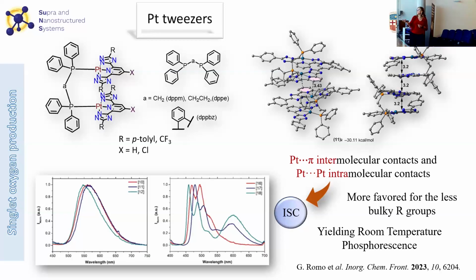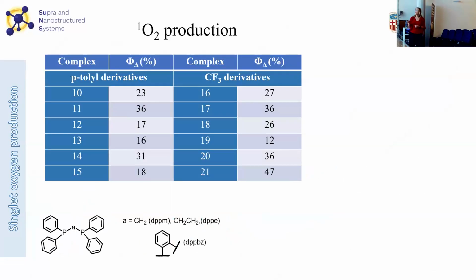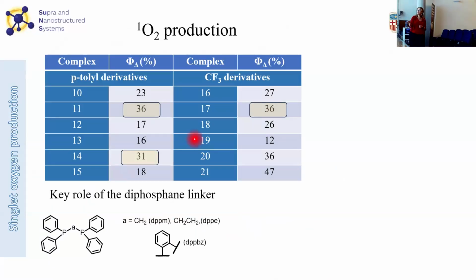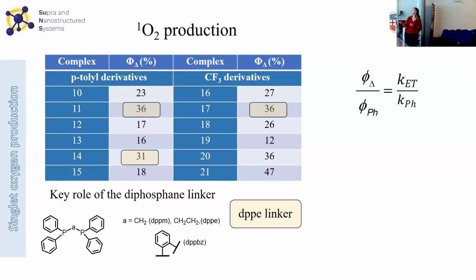And this is due to the presence of this platinum center that is enhancing again the intersystem crossing. So we were previously convinced that in fact this part of the molecule, the platinum and ligand, should be responsible for the singlet oxygen generation. But what we observed is that, on the contrary, it seems that the linker plays a key role, since these values that are highlighted here are those containing this linker with two methylene groups between the phosphorus atoms. So, contrary to what we were expecting, the linker is playing the key role in the singlet oxygen generation.